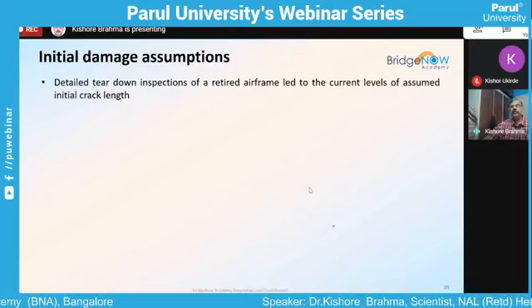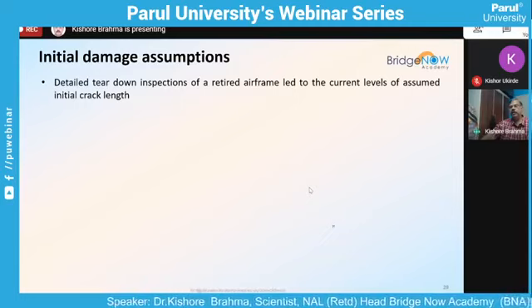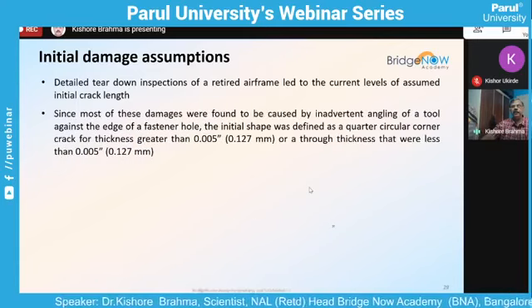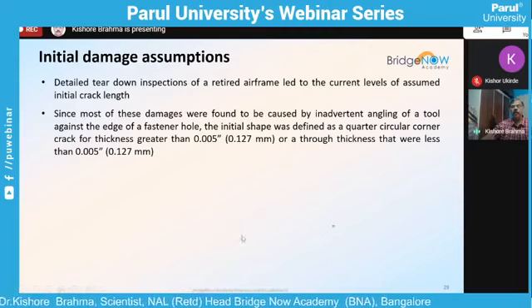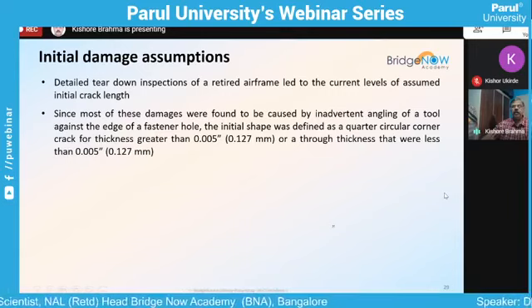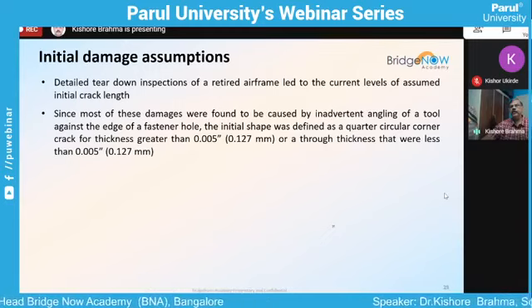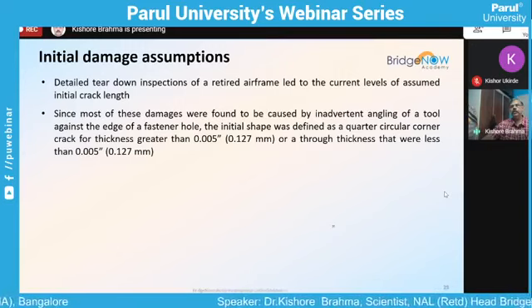Very interestingly, these initial damage assumptions were made based on an earlier, very exhaustive teardown of a lead aircraft which had already come to the end of its life. They stripped open all the primary structure, secondary structure, and wherever a crack is expected, and did some investigation using scanning electron microscope and so on. Then they found that, especially in holes, there is tool marking in the beginning. Using sophisticated techniques like electron transmission, and also by counting the number of striations induced due to the repeated load, one can do a backward calculation to find exactly what the initial crack length was and how many flight cycles it went through.